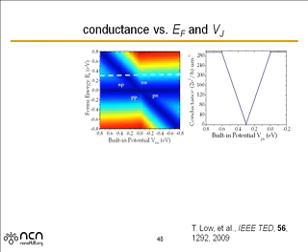So if I were just to plot the conductance along that line, it's pretty high over here on the left. It goes through this dark blue band, which is a diagonal one, and then it drops down. Then it comes out of that region, it goes back up, and it's very high again. And what's happening there? Well, I've fixed the Fermi level at 0.3 of an eV, and I'm just varying the height of this step. So when I make this step 0.3 of an eV, then the Dirac point on the right side is exactly at the Fermi level, and that's why it goes down to 0. And when I get close to that, I just get a smaller and smaller number of modes.